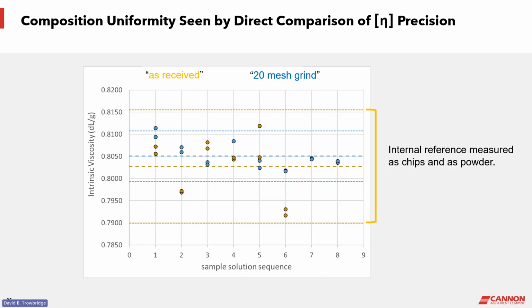And so just this simple comparison allows us to see the utility of IV precision to make a determination on this important detail. There's even an offset here that we think is probably due to longer time for dissolution, so the more heat exposure for the chips. So the chips actually go down in IV because of that longer thermal history during dissolution.